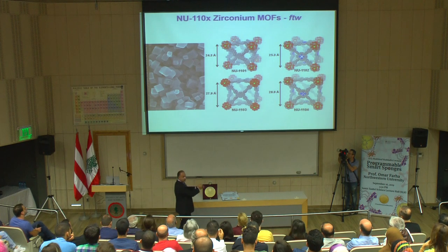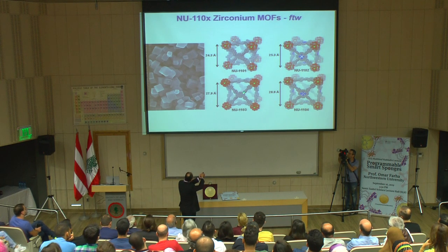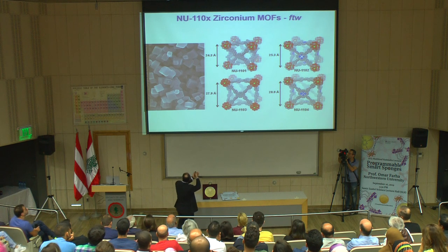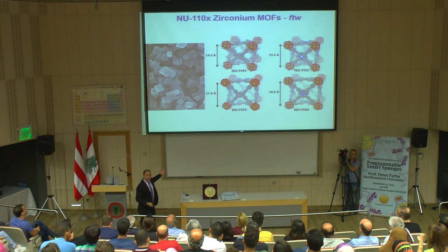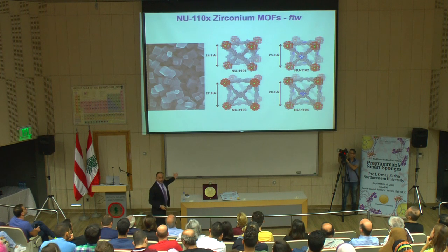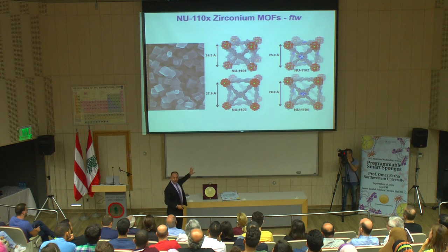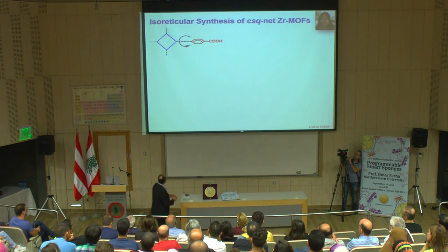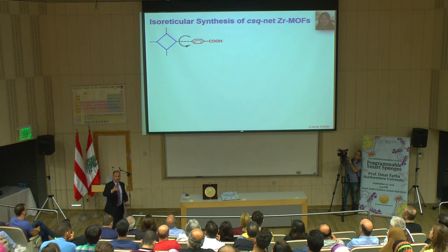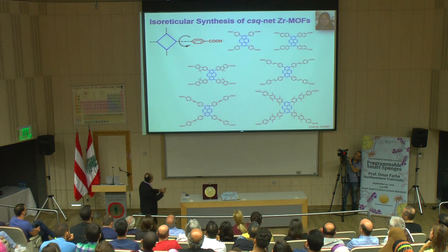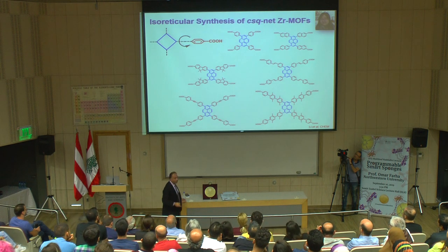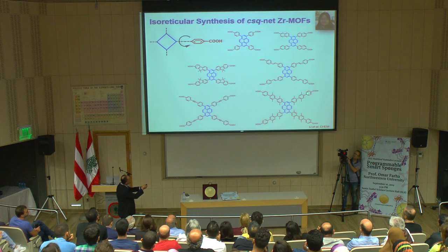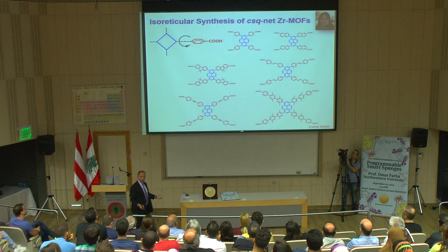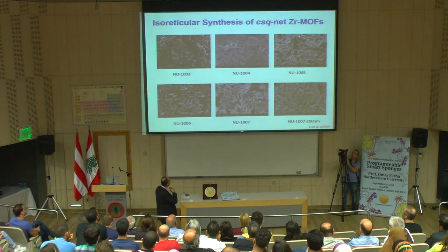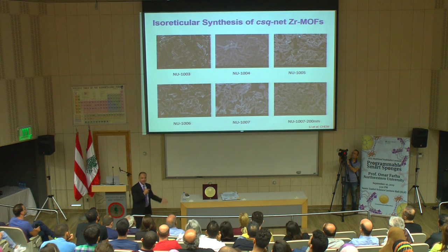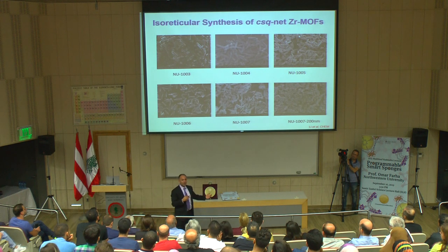We made all these planar ligands that I talked about between this phenol and this pyrene, or this phenol and this. And you could see, you don't even need a crystal structure to see this is not the hexagonal rod I've been showing you. Those are cubes. And we use these for a different application, but that tests that the hypothesis works. Now, let's go make optimized ligands that have that 55 to 65 degree angle. And we made all these ligands in collaboration with Sir Fraser Stoddart. And if we optimize them so that this rotation here is between 55 and 65 degrees, and we go and make this, you don't have any of those boxes, you get the hexagonal rods. And that's the topology we want.